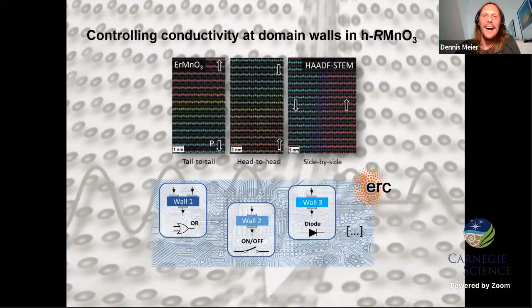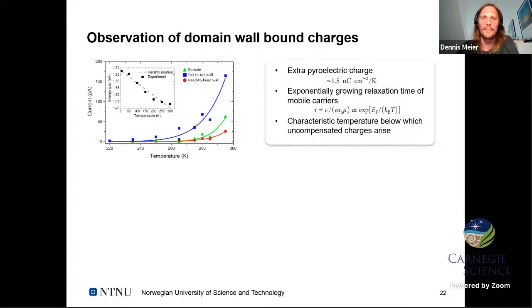Sorry for that interruption. Okay, I was just about to say that we have the different types of walls and would like to emulate the behavior of different components. How are we going to do that? I already mentioned that if we have a ferroelectric domain wall in a manganite, we have the bound charges. When we do temperature-dependent measurements of the conductance at these elements, we see nothing very special in the beginning. What you see is that tail-to-tail or head-to-head domain walls all show the same current temperature behavior, semiconducting properties, which is not very surprising because they're sitting in a semiconducting bulk material.